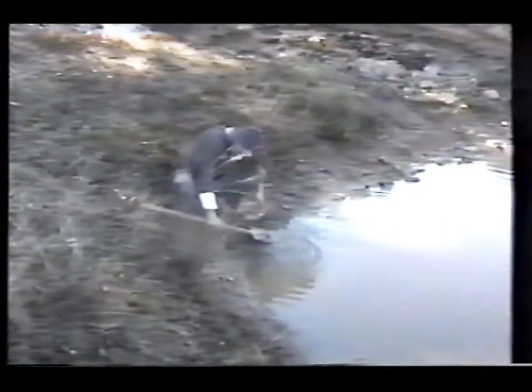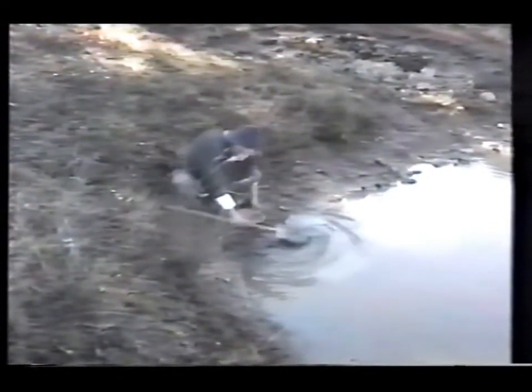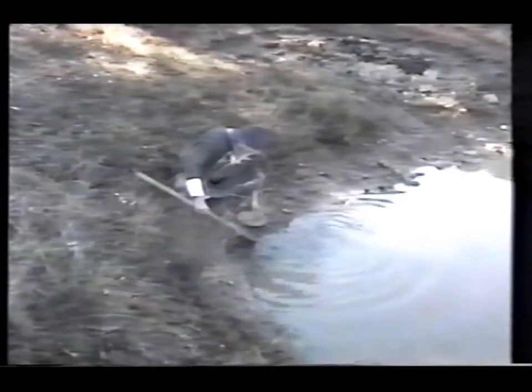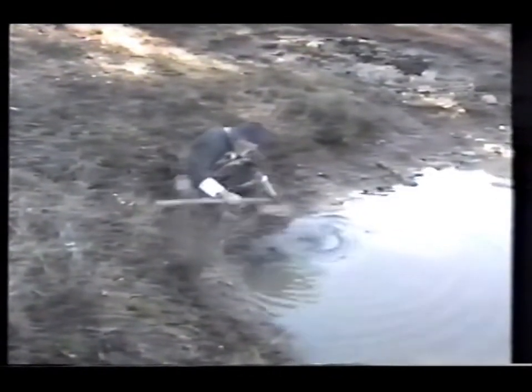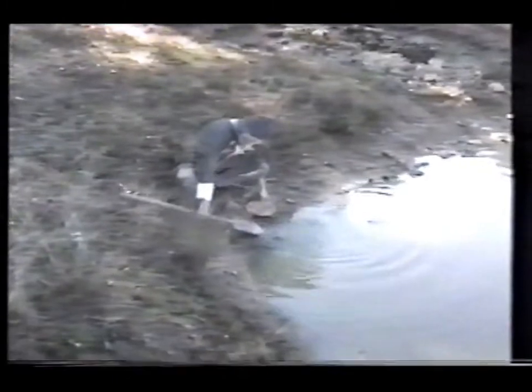These small nodules of ore. Another source of ores was magnetic sands, such as were found in rivers and lake beds, and were used by Africans to obtain a high quality ore. Some of these magnetites are up to 70% iron. The average would be about 50 or 60% iron. It varies considerably. These were panned for, much like gold was in the old days.